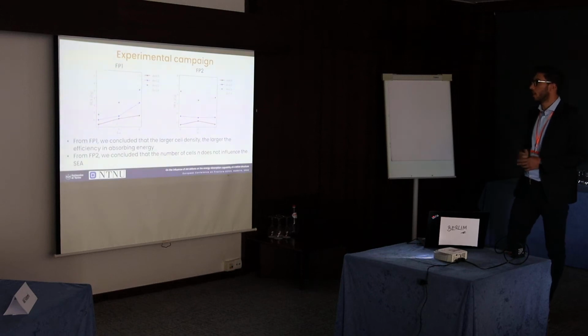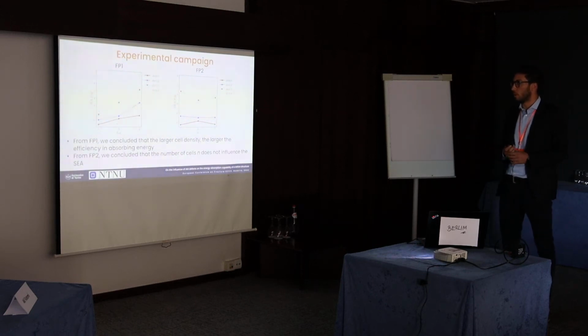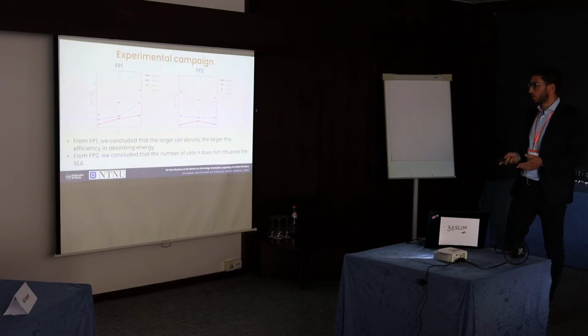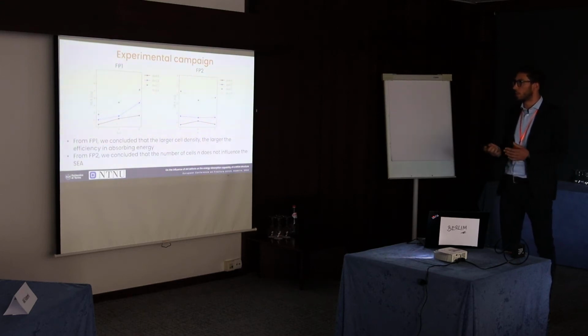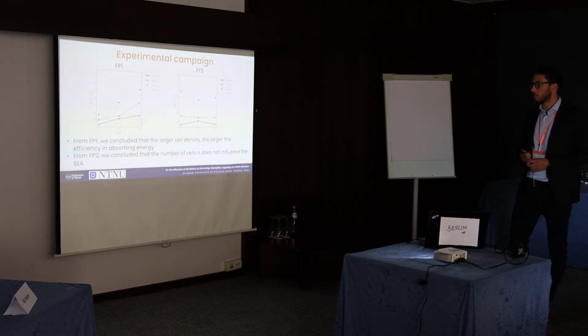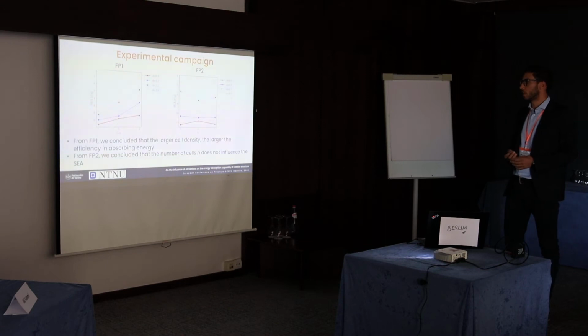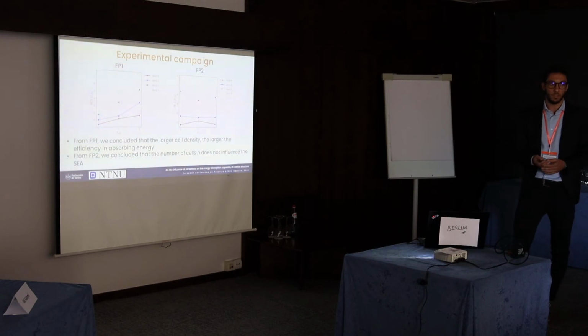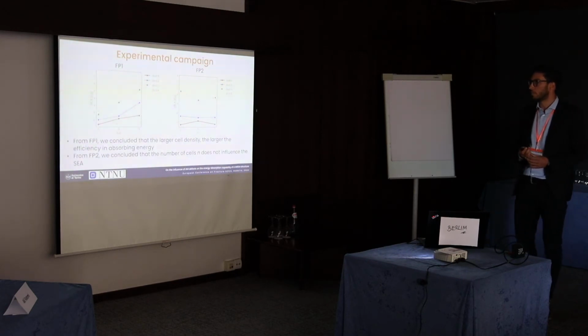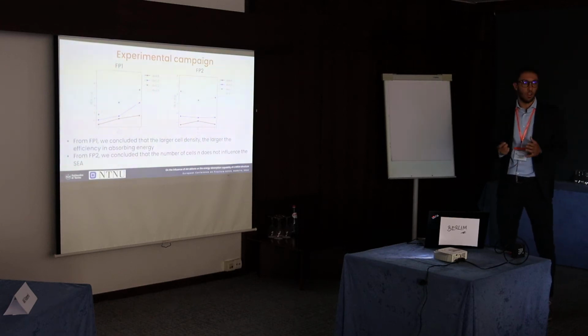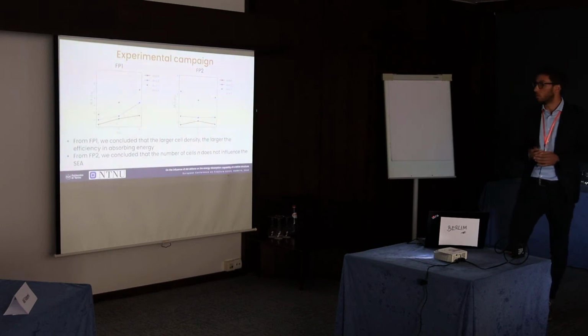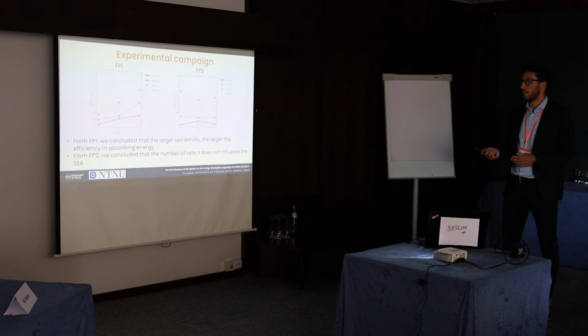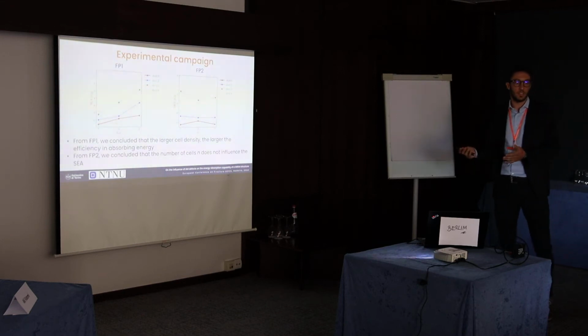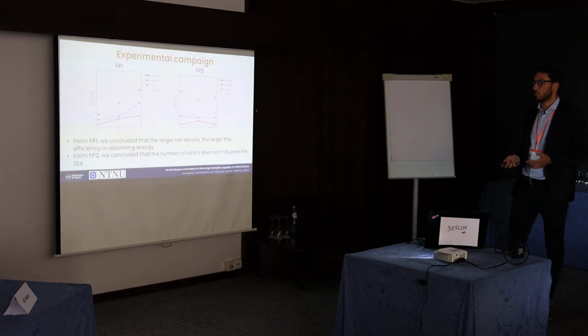Instead, here in the figure on the right, we have the results of the second factorial plan, where again it can be appreciated that the specific energy absorption increases with the diameter of the beams. And also that the number of cells does not influence the specific energy absorption, which is a really important result because it means that we can evaluate the specific energy absorption of a unit cell on a specimen made of a small replication of the unit cell, and then we can use this result in the design of a component that is made of several replications of the unit cell.